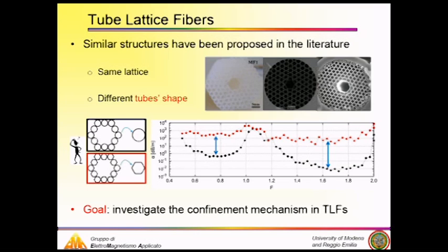As I told you at the beginning, different structures have been proposed. As you can see from the picture here, they are actually very similar. What changes is the shape of the tubes used in the cladding, circular or polygonal, in particular hexagonal. Even though they are very similar, they have very different performances in propagation loss. In particular, if you consider the Kagome fiber with the hexagons in the cladding, you have much higher propagation loss than the circular case.